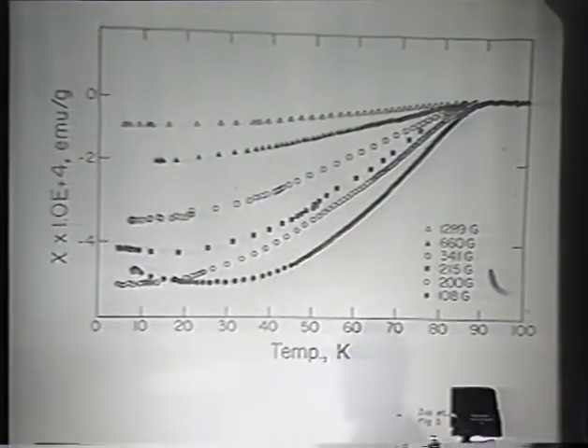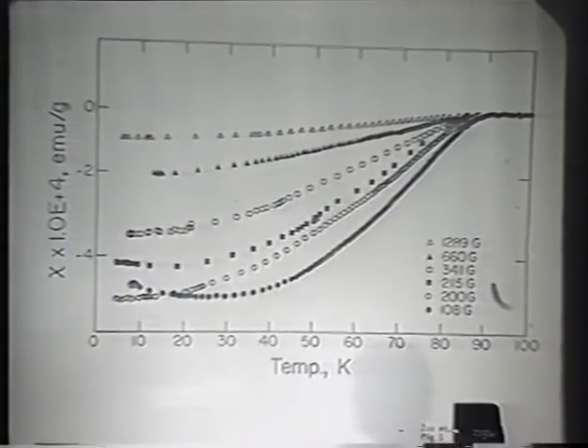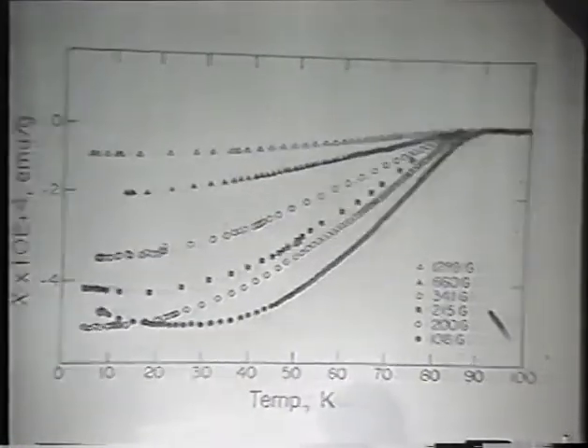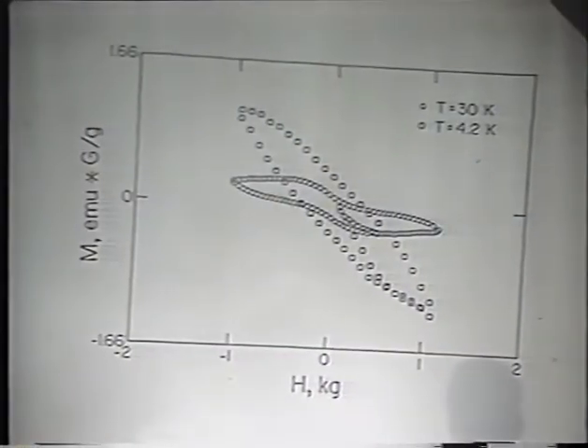I want to show you quickly just a few hysteresis loops that we have in our superconducting state. These are field-cooled susceptibility measurements, and we get about 25% of the full minus 1 over 4 pi susceptibility on the field cooling. The hysteresis loops are interesting, and they allow us to pick off the lower critical field, HC1. I don't think you've seen loops like these tonight, but these are complete hysteresis loops going through zero field. We have those as a function of temperature right up to the transition temperature.